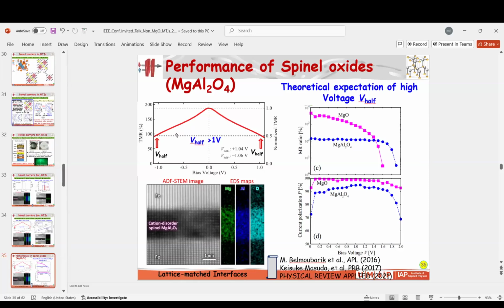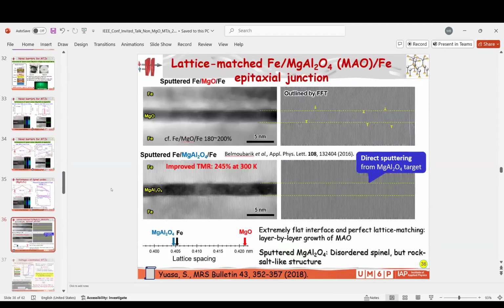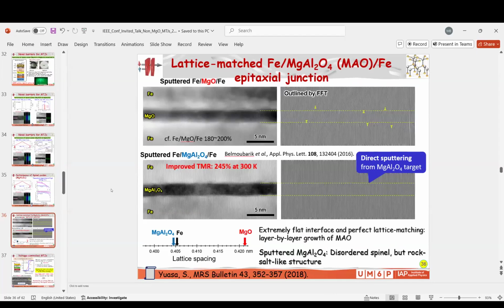In the case of magnesium aluminum oxide, this can be done easily. We can reach 1 volt easily. So this has been confirmed by a physical calculation by Professor Masuda of NIMS. Here is the FFT of the TEM images that shows the diminution of dislocations once we use the spinels.